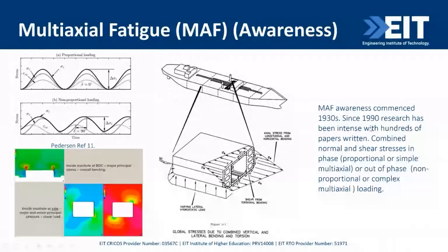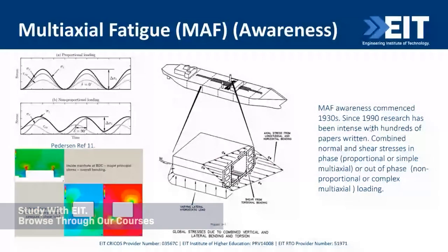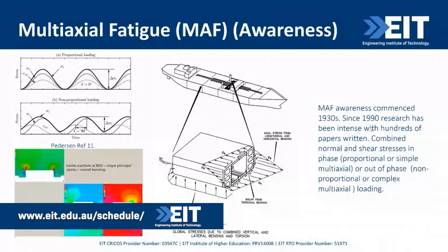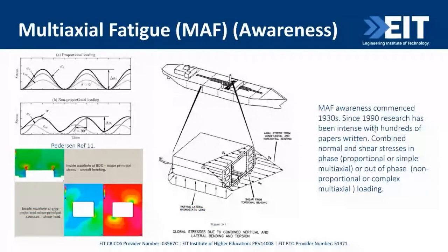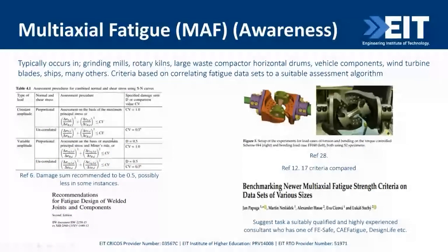So, multi-axial fatigue work commenced in the 30s. And over the last 30 years, it's been absolutely intense, with hundreds of papers written, and it's still ongoing. It's not certain when it'll finish. It'll probably never finish. But to cut it short, the IIW codes recommend a damage ratio of 1, which is your normal damage ratio. But for non-proportional loading, they go down to a damage ratio of 0.5 and even less. And BS 7608 has the same conclusion, but it's not well written, it's only in text. It's not well compiled, unfortunately. But that's the guts of it.